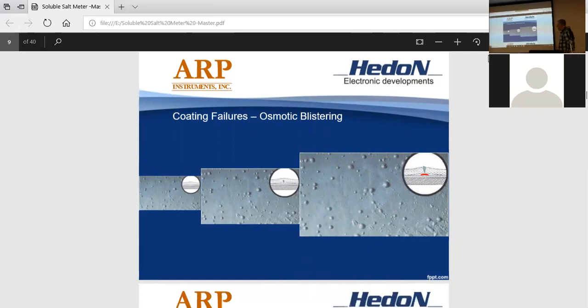So here's a little slide I was trying to use to illustrate basic things. So you get blistering, and can you see this pretty good? Mm-hmm. So the coating fractures because of the pressure on the coating. It's more rigid, and when it breaks, you get migration of seawater, and then you get corrosion started, basically underfilm corrosion going, which is even worse. And that's why you see the growth of the blister. Underfilm corrosion, which is even worse.